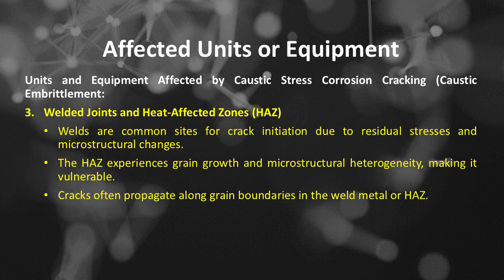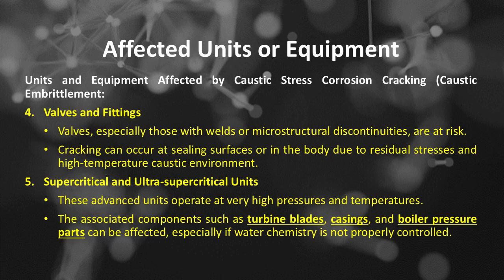Number 3 of units and equipment affected by caustic embrittlement is welded joints and heat-affected zones. Welds are common sites for crack initiation due to residual stresses and microstructural changes. The HAZ experiences grain growth and microstructural heterogeneity, making it vulnerable. Cracks often propagate along grain boundaries in the weld metal or HAZ. Number 4 is valves and fittings. Valves, especially those with welds or microstructural discontinuities, are at risk. Cracking can occur at sealing surfaces or in the body due to residual stresses and high-temperature caustic environment.